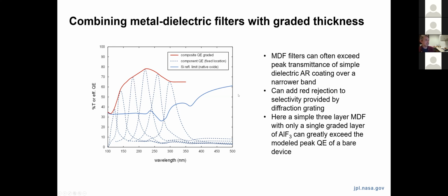And so this is just an example of a modeled, relatively simple 3-layer coating with only a single graded thickness layer of aluminum fluoride, and then a single metal layer of aluminum that can, in principle, create a spectrograph that has a significant increase in effective quantum efficiency versus a bare device, again, with the benefits that you get from the red rejection at longer wavelengths as well.